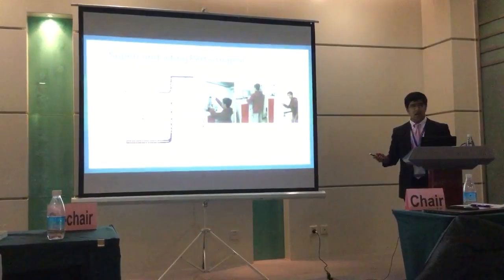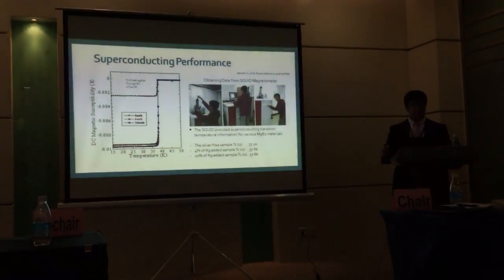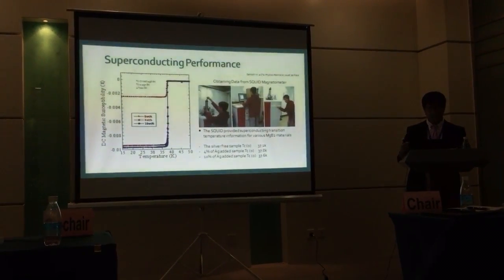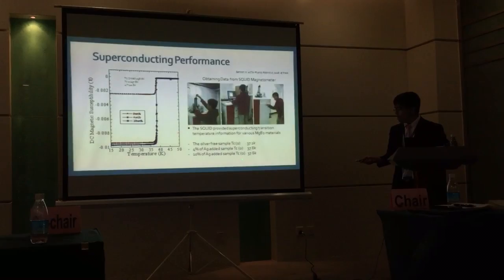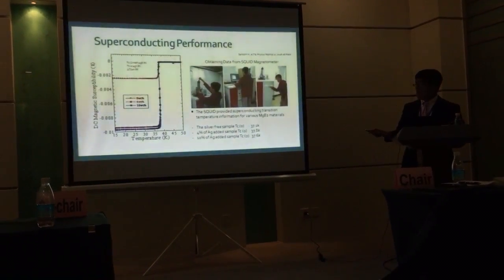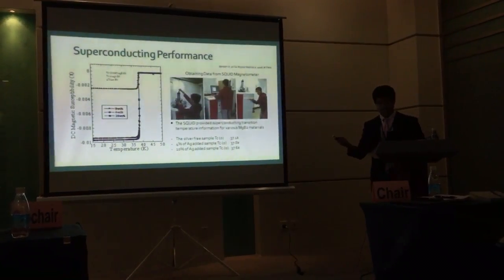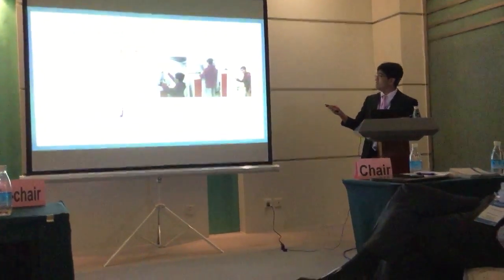For silver free, it was 37.1 Kelvin, for 4% addition of silver, it resulted in 37.8 Kelvin, and for 10% silver addition, it ended up with 37.6 Kelvin. And this is the following graph. This data is currently in press at Acta Physica Polonica A, which I'll be discussing further.